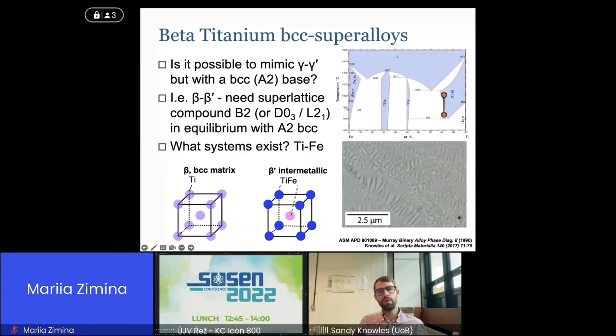And so we've done a number of bits of work looking at trying to use this binary as the base to create a beta-beta prime or a beta titanium BCC superalloy. So taking the titanium matrix and having precipitation of titanium iron, and you either get spherical or lamellar precipitation structures. So we've done work looking at the strength and the formation of these microstructures.